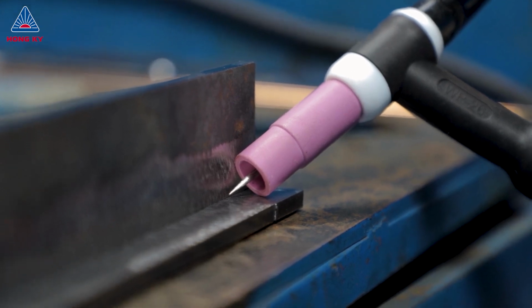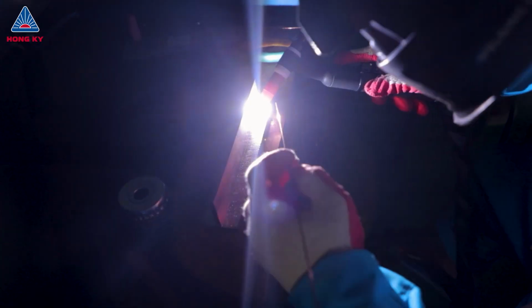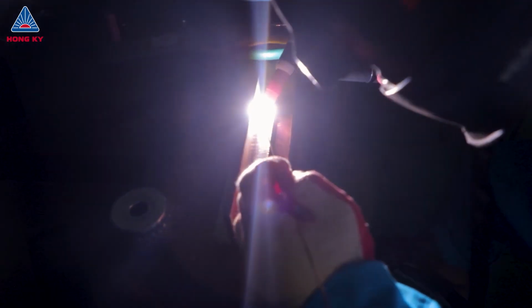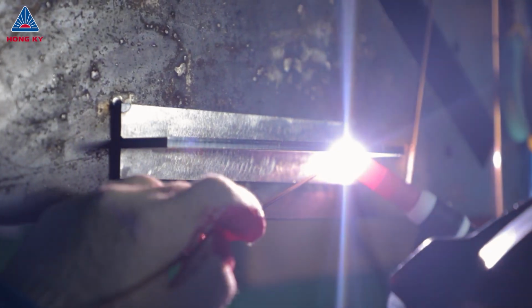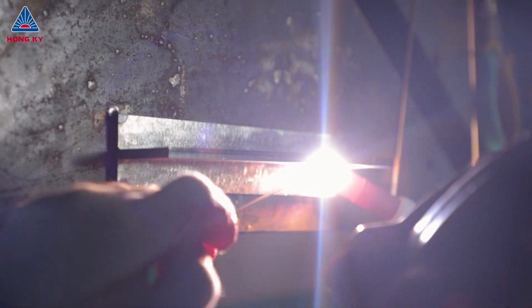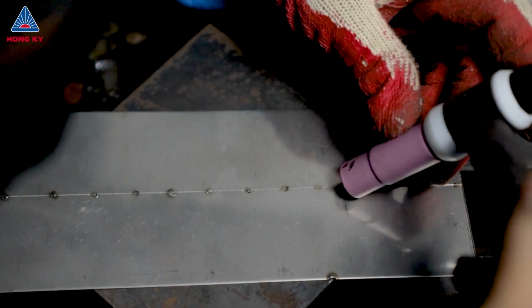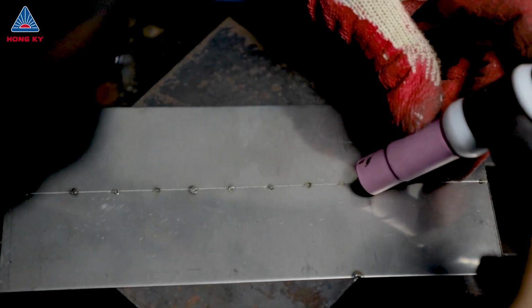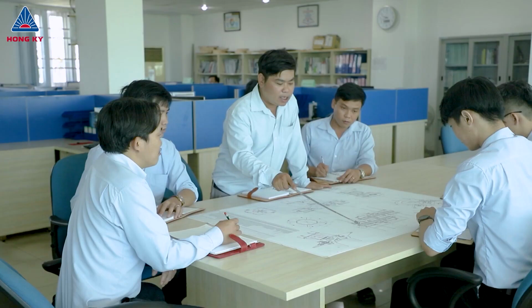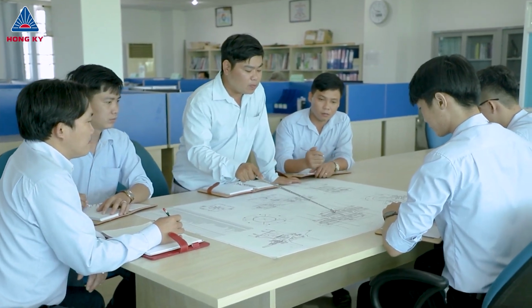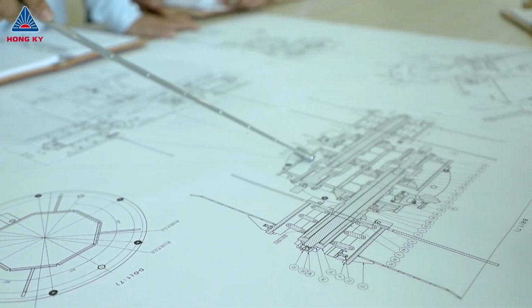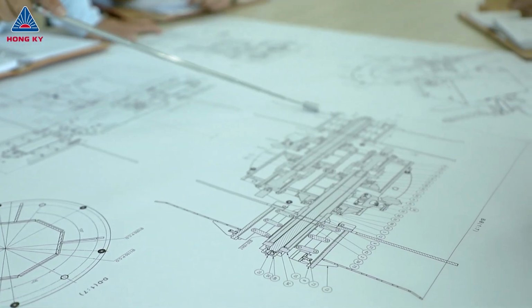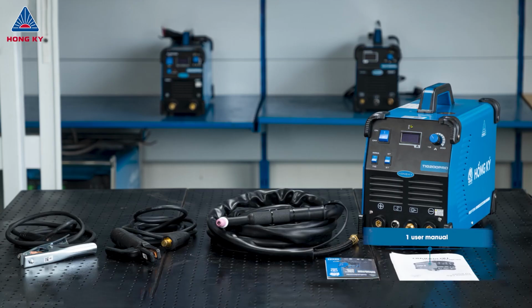Moreover, to achieve the best welds, pay attention to your welding speed and ensure a steady hand. If the welding speed is too slow, excessive heat will be applied to the weld, causing it to overheat and appear gray. Regarding thin material welding, the TIG 200PRO can weld steel as thin as 0.5 millimeters using the spot welding method, applying continuous trigger pressure. These parameters have been carefully researched and measured by the product development team at Hong Ky. Therefore, welders can confidently refer to these specifications included in the user manual that comes with the machine.